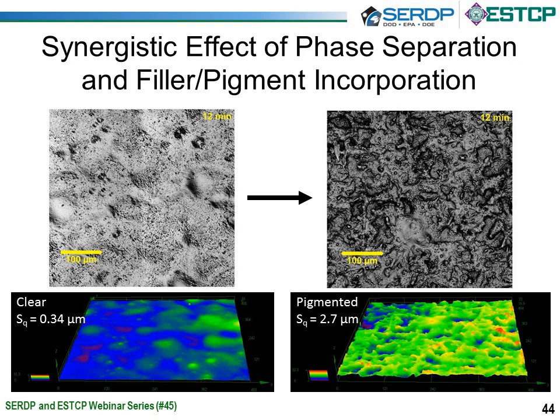On the left, we see the laser confocal at 12-minute cure of a clear system without the addition of pigments and fillers. And on the right side, we see a 12-minute cure of the same polymer system, but this time incorporating pigments and fillers. You can see that there's a dramatic increase both in visual and in surface roughness, as noted below, and this is absolutely necessary and essential for the down gloss of these coating systems. And the root mean square on the lower left for the clear shows 0.34 microns, where the pigmented system on the right side is 2.7.